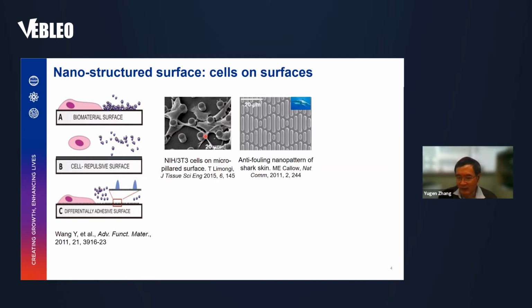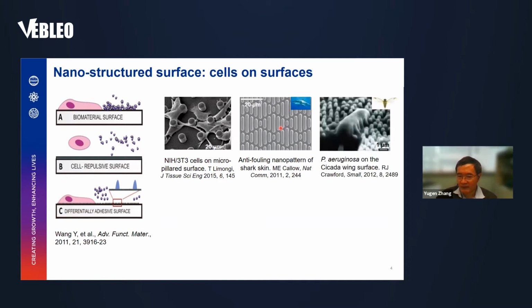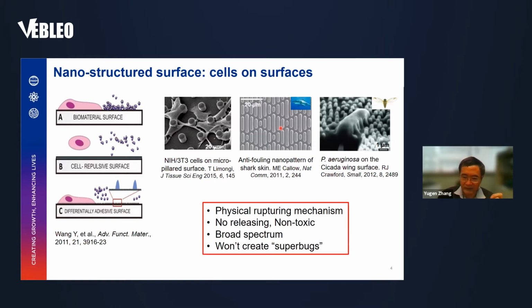But if the parameter of the nanostructure is between 1 micron and 10 microns, then typically this type of surface will repel the cells. For example, shark skin is a well-known one that will repel microbes or other features. But if the surface nanostructure parameter goes further down to the sub-micron scale, then this kind of nanostructure will kill the attached cells, and this we consider a physical rupture mechanism. There is no toxic chemical release. We can consider it a non-toxic killing mechanism. They generally have a broad spectrum because they do not target a specific target. They just penetrate the cell membrane, cause lysis, and they have much lower opportunity to create superbugs.